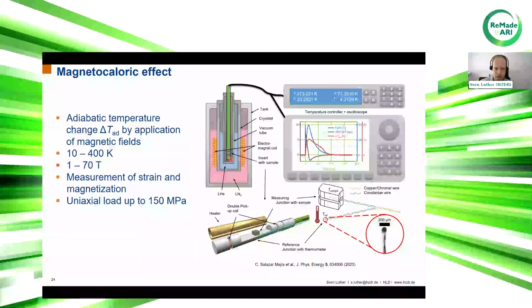In addition to the magnetocaloric effect, we can also do simultaneous measurements of the strain and the magnetization, and also put an uniaxial load of up to 150 megapascal. The measurement is done in the following way. You can see a sketch of the sample preparation. We have the sample sitting here, and here we have our double pickup coils to measure the external magnetic field from our pulse field coil.